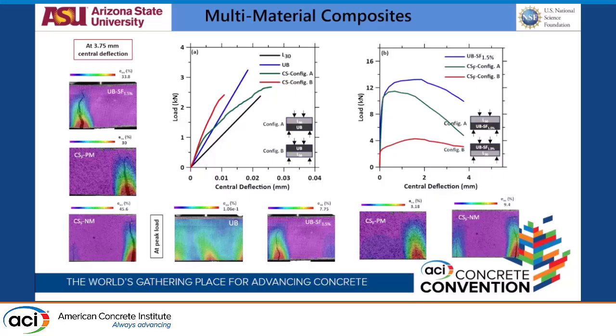The significant observation comes when you are using a steel fiber mix, shown on the right-hand side. The blue line on the top is a homogeneous beam. You have the UBSF 1.5% there, so everything has steel fiber from bottom to top. But the green line that you see has steel fiber from the bottom to the half of the beam, while from half to the top there's no steel fiber. It's an L30 mix now. So technically you have half the volume of steel fiber being used, and you can see the ductility is lost because of the reduction of steel fiber, but you are still getting just a 15 to 20% decrease in the overall load carrying capacity of the beam.